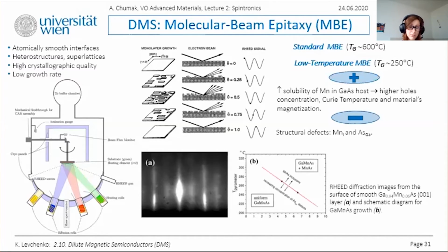Of course, it includes RHEED diffraction during the growth procedure. So the high resolution X-ray diffraction, the TEM and SEM images, and the SIMS plots, they all confirmed the very nice and high quality state of the gallium manganese arsenide that we are now able to grow.